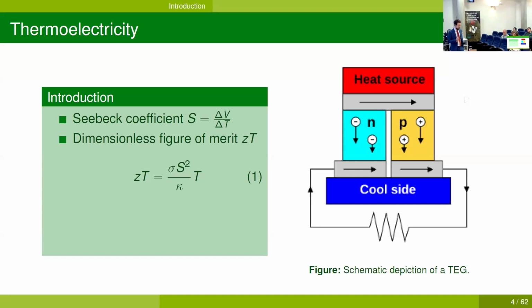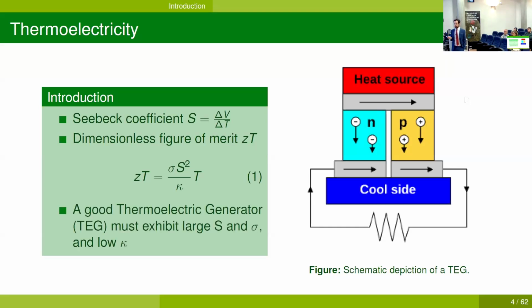In order to measure the conversion efficiency, we can define the dimensionless figure of merit, ZT, which is defined as the ratio between the electric conductivity sigma times the Seebeck coefficient squared, divided by the thermal conductivity kappa times the operational temperature T. Therefore, a good thermoelectric generator must exhibit a large S and sigma and a low kappa.